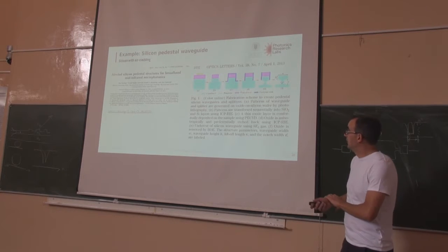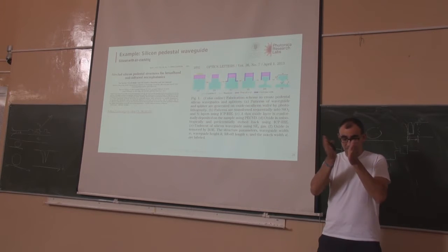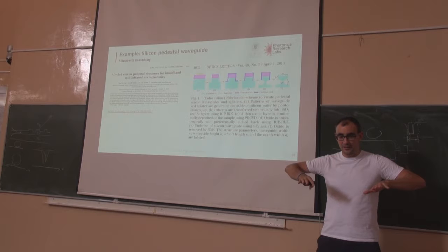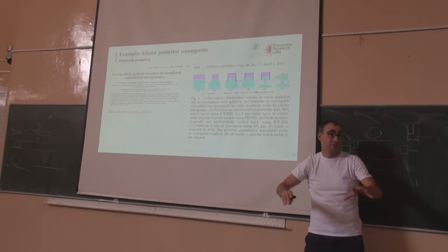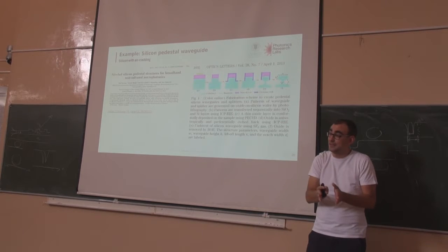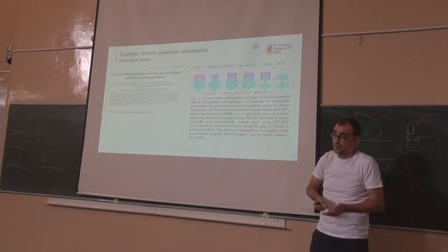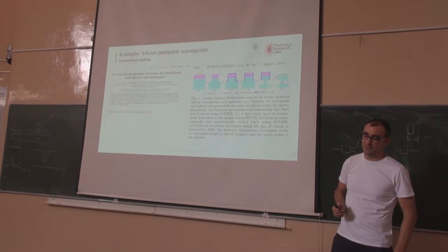Problems of this. Basically, when you etch these kinds of structures, it depends on the density of features. Where there is more density, they are etched less. Where there is less density, they are etched more, even broken completely. So this also has some fabrication difficulties.